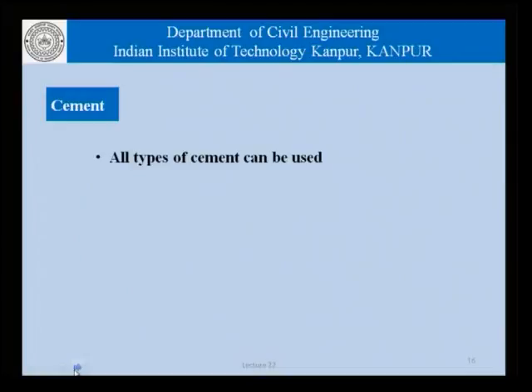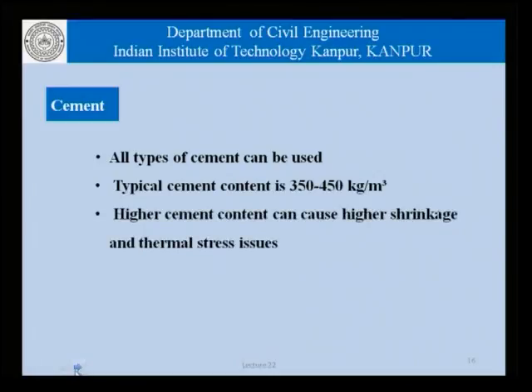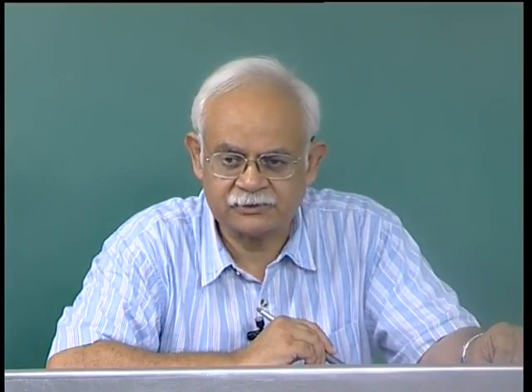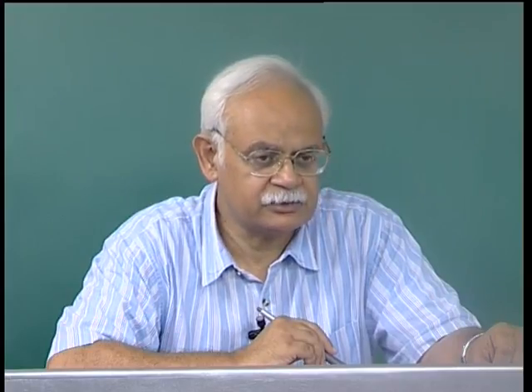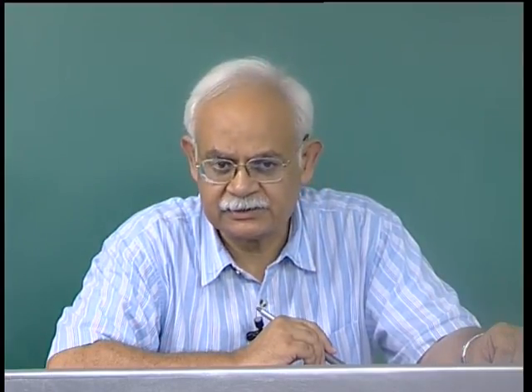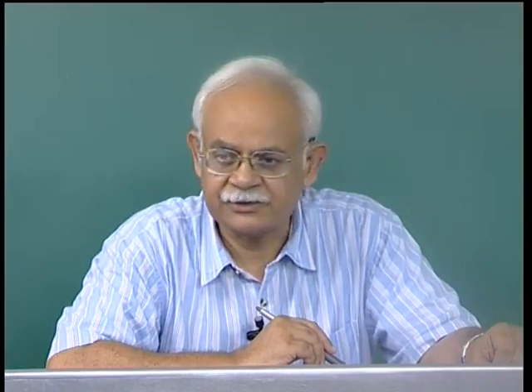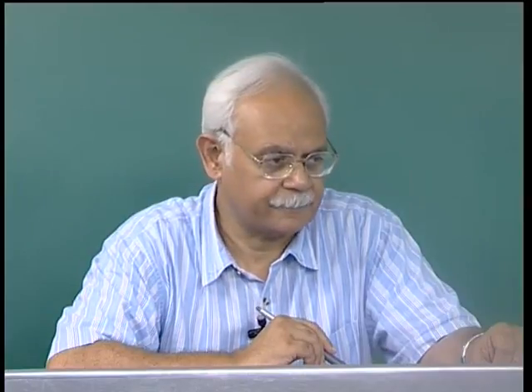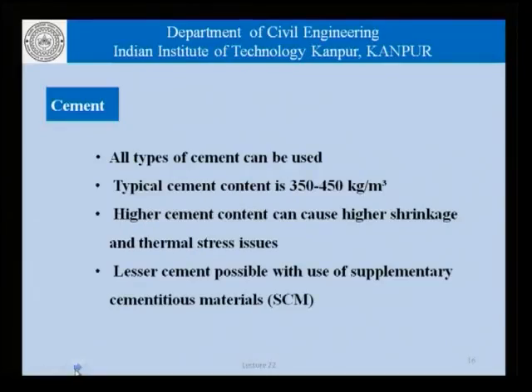As far as cement is concerned, we can obviously use almost any type of cement. The typical cement content is no different from normal concrete. It is about 350 to 450 kgs a cubic meter. And if we use higher cement content, obviously, we will land up with higher shrinkage and thermal stress issues. And therefore, even though we require a higher paste volume or a higher powder volume in the paste, it is not always advisable to use cement. We would rather use materials of similar fineness, but not having the hydration related issues in terms of heat and so on. And as we have stated, lesser cement content is possible by the use of these supplementary cementitious materials.